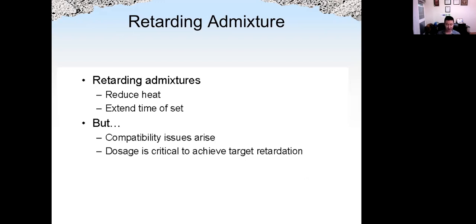For retarders, it will reduce the heat and extend the setting time. But again, potential compatibility problems. When you combine different types of admixtures, always check if they will interact with each other. And dosage is very, very important. Too much retarder, the concrete may never set. And what time you add retarder is also important, as one of the problems in the field. Delay 10 minutes in adding the retarder, you may increase the effectiveness of the retarding agent.